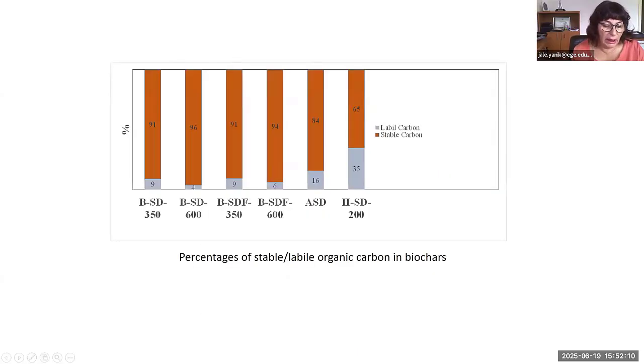The carbon stability allows biochar to remain in the soil for a long time. Labile carbon refers to unstable carbon. High stable carbon content is ideal for long-term carbon storage, as you know already. The amount of labile carbon is related to volatile matter, but interestingly, labile carbon is rapidly metabolized by microorganisms and provides short-term soil fertility. And the biochar obtained from wet carbonization has a high amount of labile carbon.